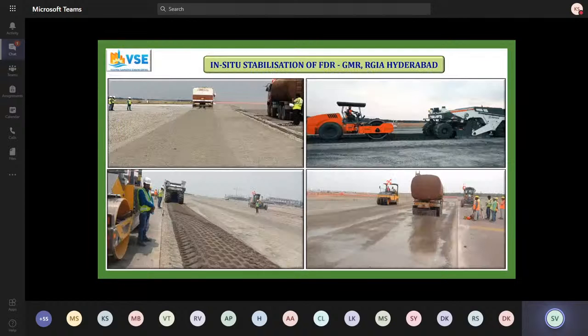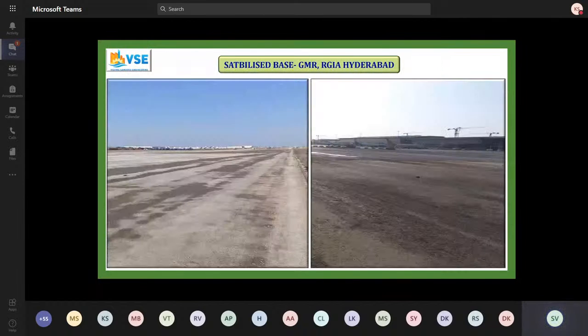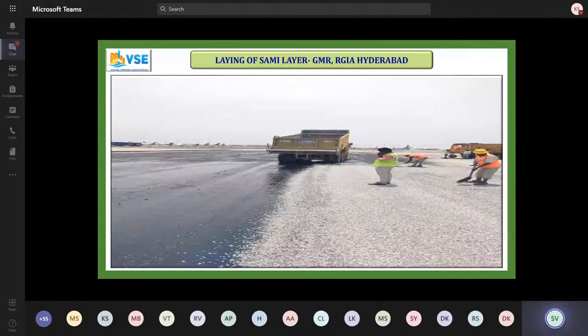These are the pictures of in situ stabilization. We spread cement and then recycled, and then we went for a SAMI layer. We used the chip spreader, which is totally automated. First we put PMB 40, then laid the chips on top of it, and then rolled it. The consultant for GMR asked us to do two layers of SAMI, so we did two layers, one on top of the other, before going for SDAC and DAC.